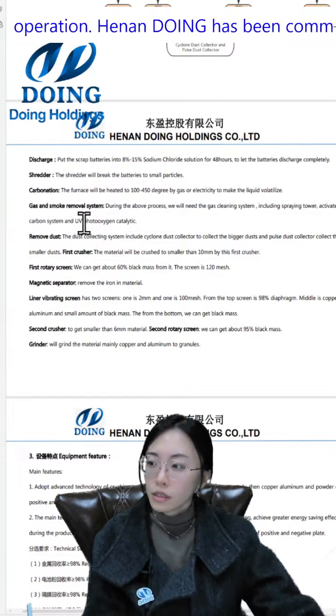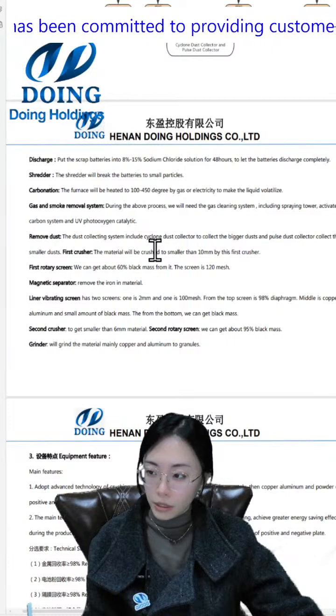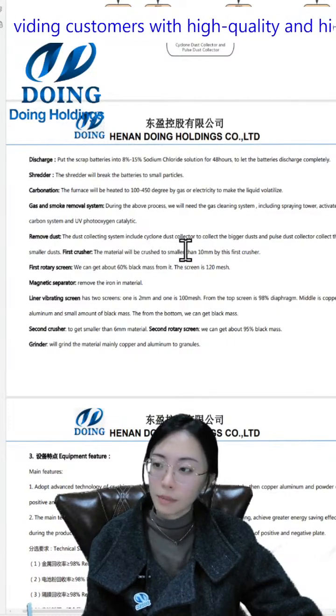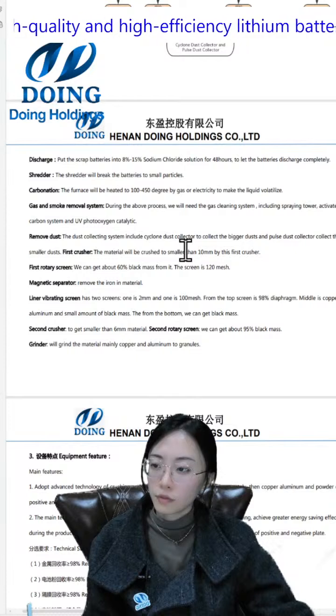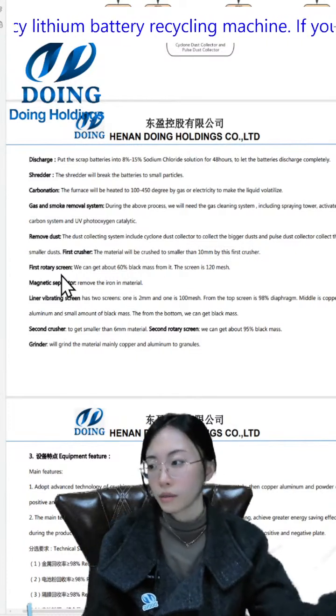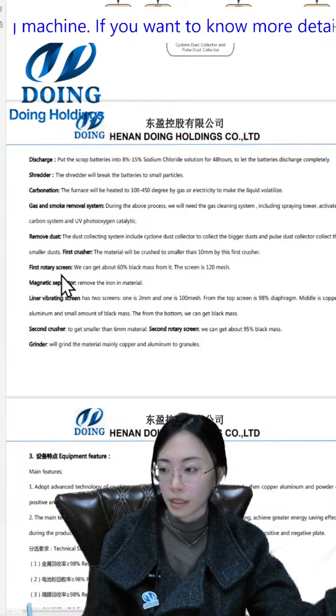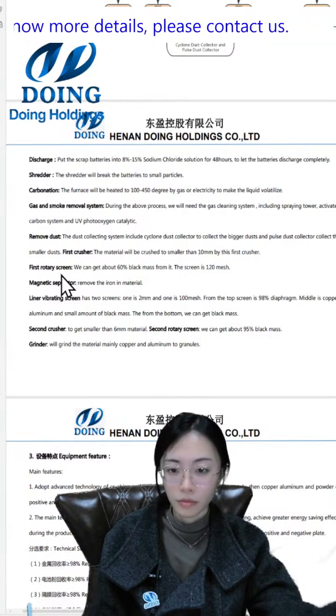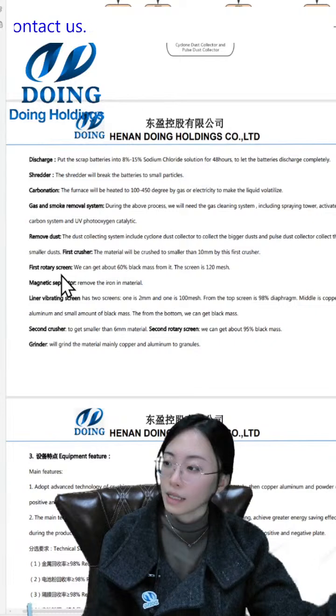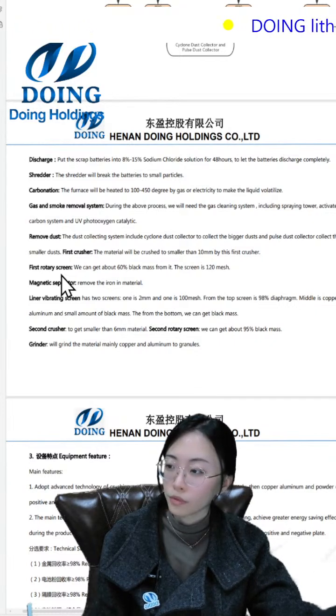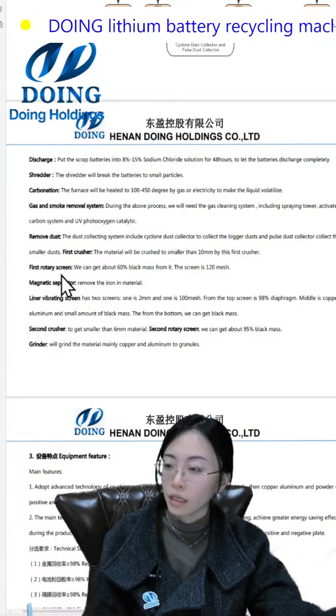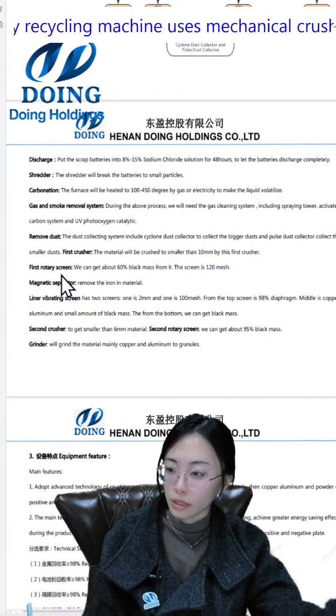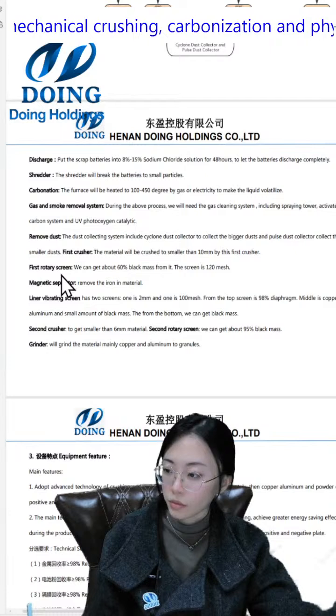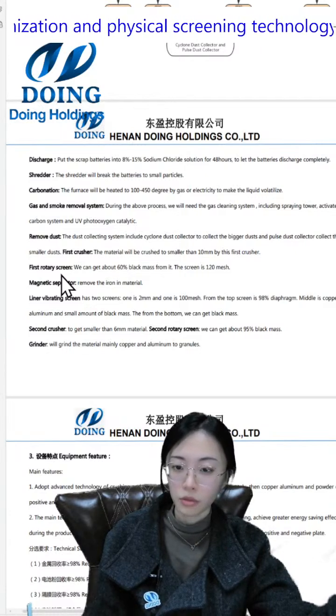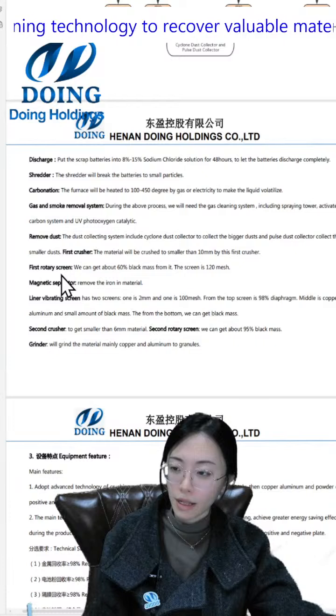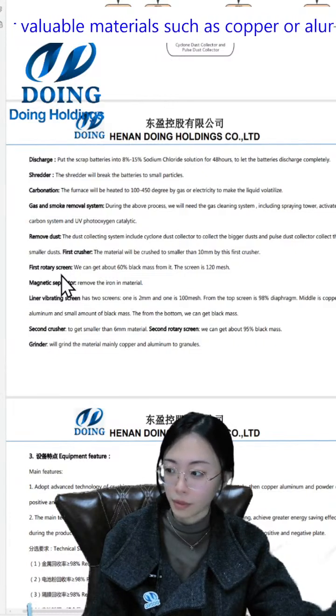And then the material will be crushed to smaller than 10 millimeters by the first crusher, and from the first rotor screen we will get about 60% black mass. The screen is 120 mesh, and then the magnetic separator removes the iron, then a vibrating screen removes the diaphragm, and the second crusher crushes the material to 6 millimeters. The second rotor screen gets about 95% of the black mass.